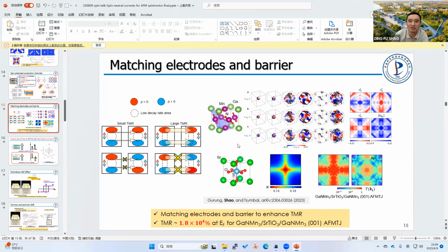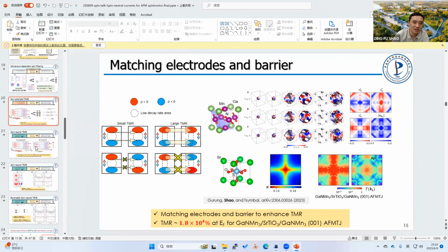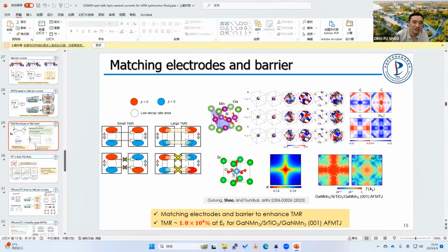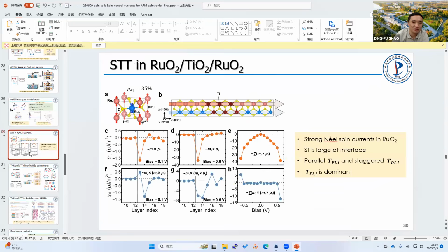I don't have a direct answer to what is the best area. Well, I think the matching is specific. This may match this material, but will not match other material. But in the second half, which will be tricky, because as Kirill said, we have this Néel spin current, which means if the current generated from here flows across a barrier, we need this current started from here to be injected into the same sublattice in the red electrode.